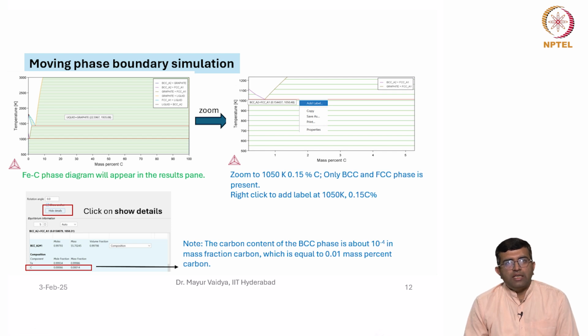The lines that you see here represent the ferrite region. We already saw that it was only 1 nanometer, which is very small against the width of the austenite. Now in region 2, set the phase to FCC-A1, which was the other phase we saw on the phase diagram, the BCC plus FCC region. Then again for the composition profile, click edit. You will see this window opening, and keep this setting: dependent component is iron, carbon linear profile from 0.15 to 0.15. Then click apply, and these are the compositions we have defined.